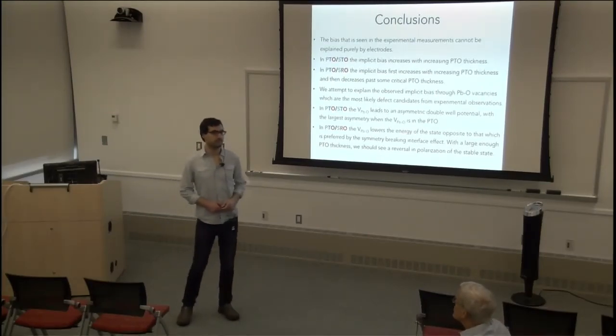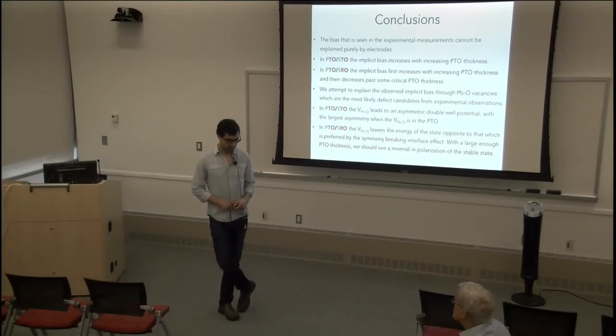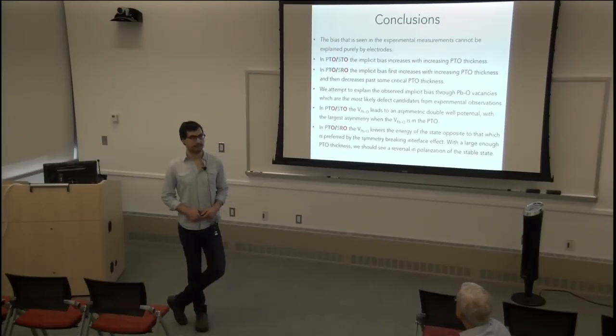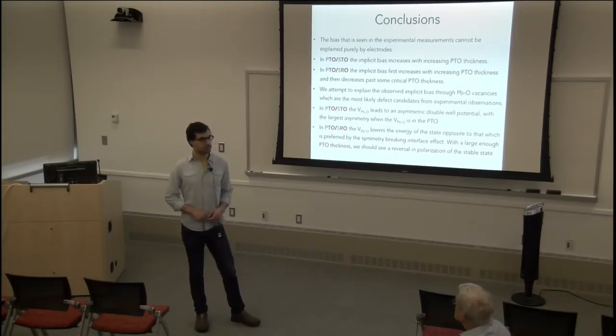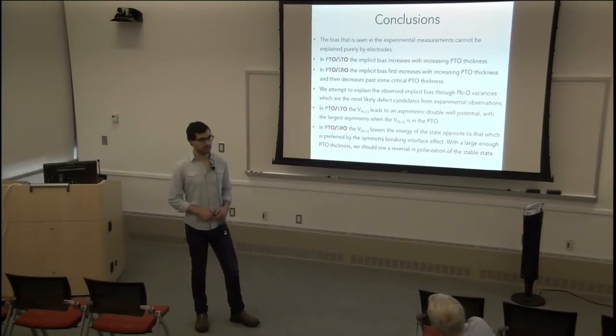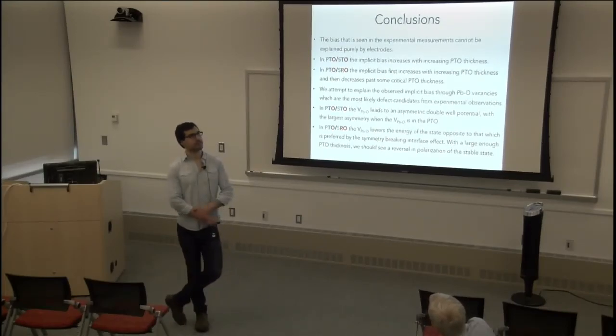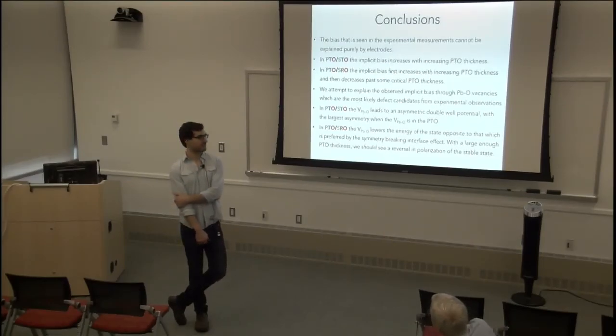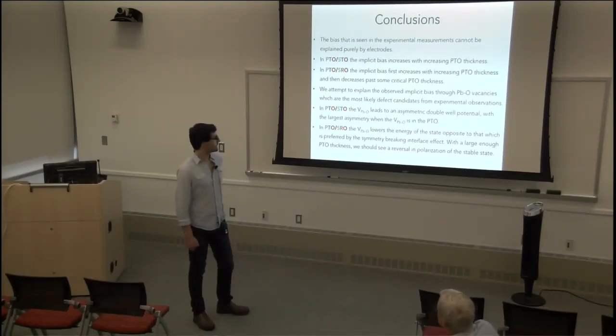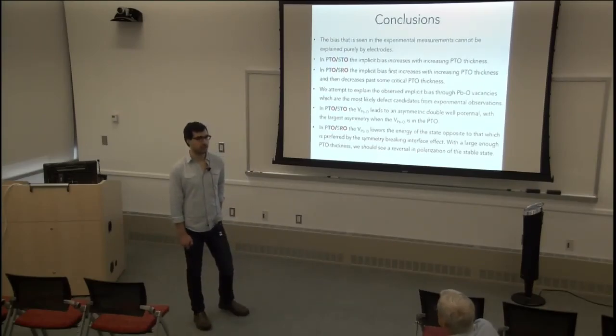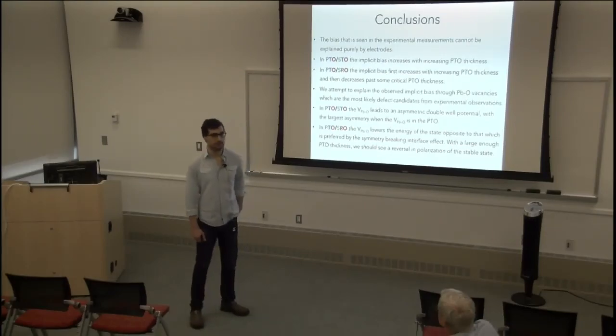One more question. Yeah. So, we know a lot about the defects in materials like silicon. Point defects. And these divacancies in these layered materials seem to be an important defect. But in silicon, we have ways of probing the defects experimentally. For example, at room temperature, they release carriers, and you can measure the carrier density. And at low temperatures, they bind states, and you can measure the optical properties of the bound states. Also, silicon is a much simpler material, and you can grow very high quality, very pure silicon, right?